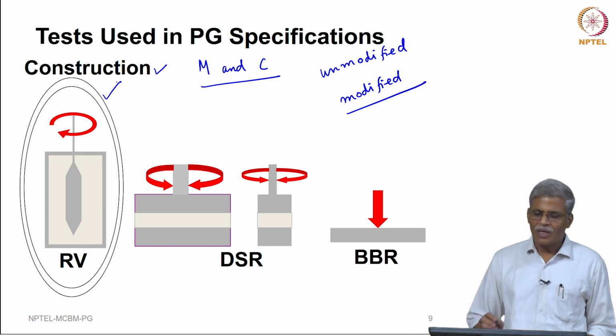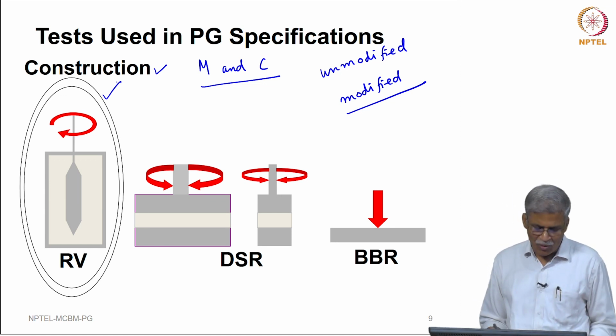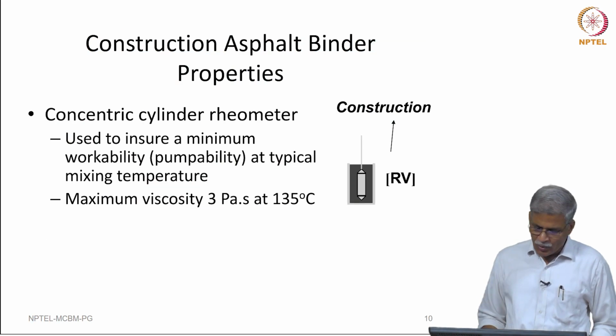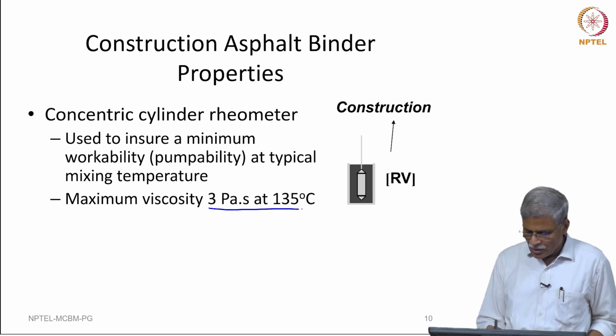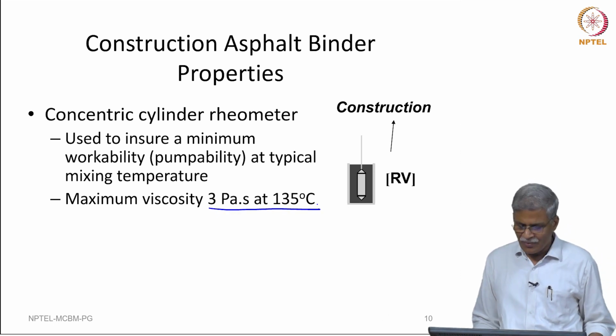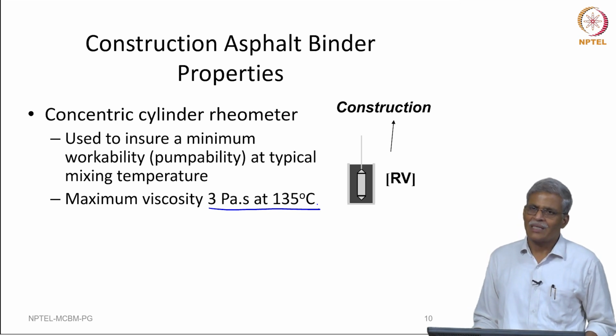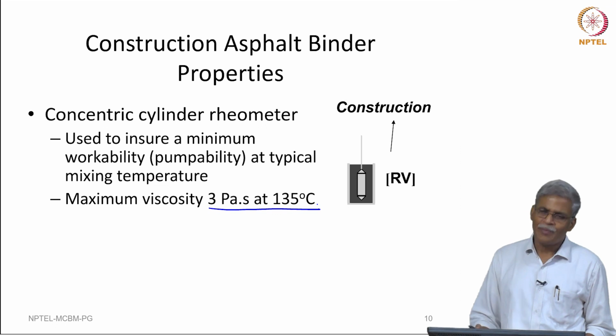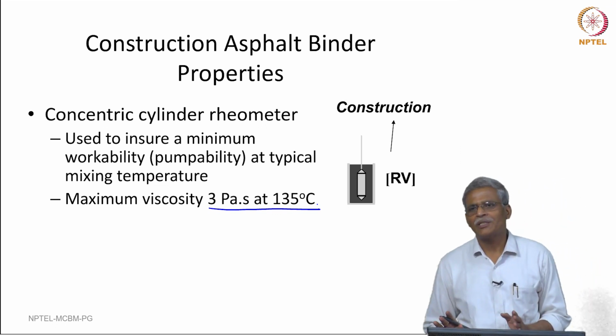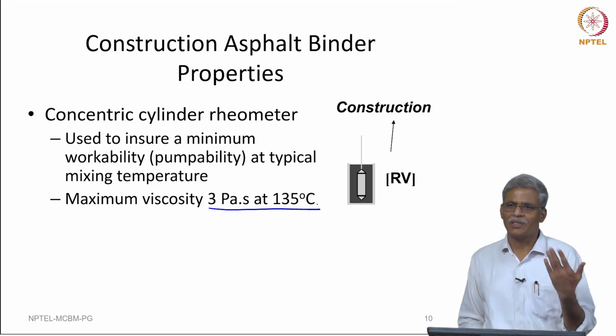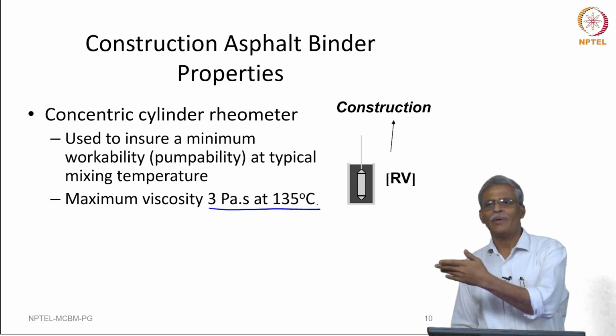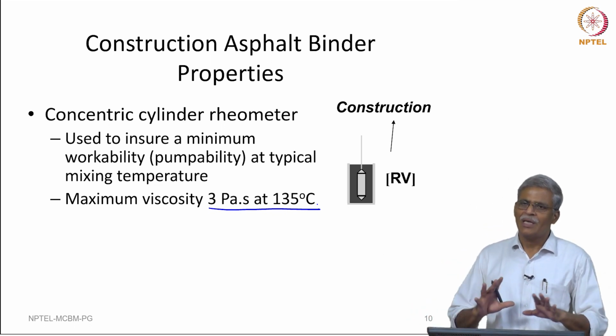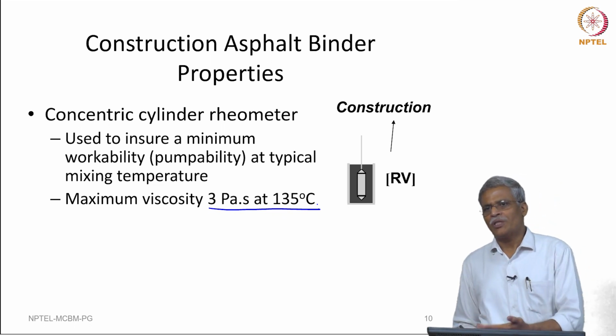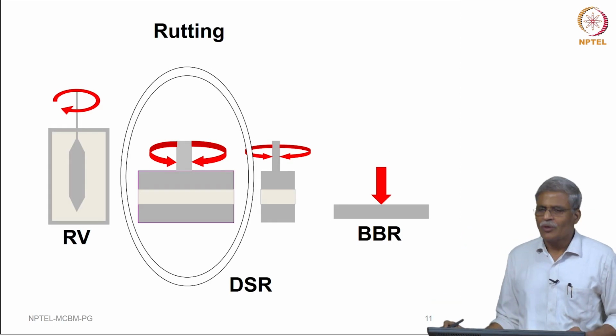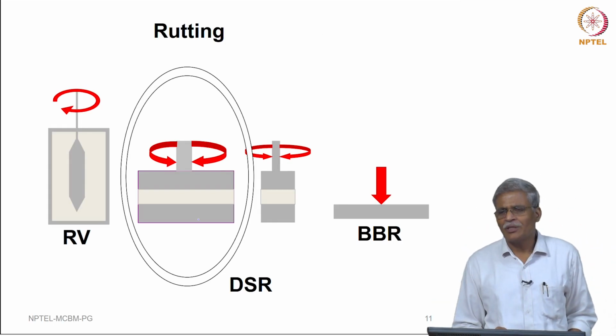So, as of now, for construction purposes, we are going to use a rotational viscometer. And what are we going to do with this? We will be finding out the viscosity at 135 degree centigrade, and we expect that the maximum viscosity will be 3 Pascal second. And in fact, at this temperature, the material is expected to be Newtonian. So, this 3 Pascal seconds is just a straightforward implementation in SI unit. In the olden viscosity based specification, it was given in centistokes using kinematic viscosity. So, there is absolutely no change in this, except that Superpave prescribes that you have to measure it with a rotational viscometer, right.